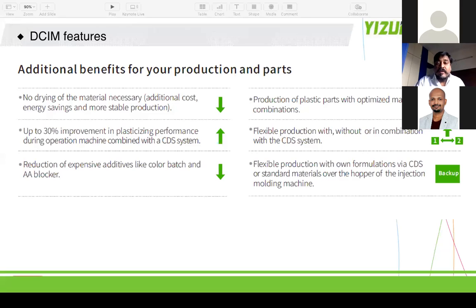Also, when you use glass filled or fillers, first you do the compounding, then you are breaking the fillers' length. Also, you are breaking the quality or the strength of the fillers. Again, you are remelting or redrying on an injection molding machine where you are again plasticizing. Again, the performance is reduced because you're breaking again the fiber length and also the strength of the fiber. So that means you're heating, preheating, and plasticizing two times. One is in the compounding and one is in injection molding machines. Here it is only one time direct compound injection, so it improves 30% in plasticizing performance, which improves the quality of the final parts also.